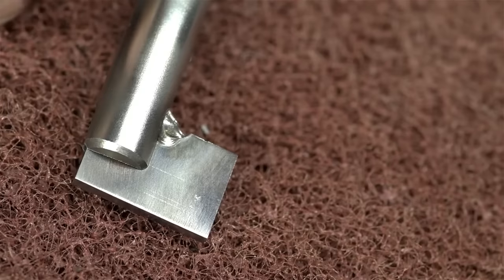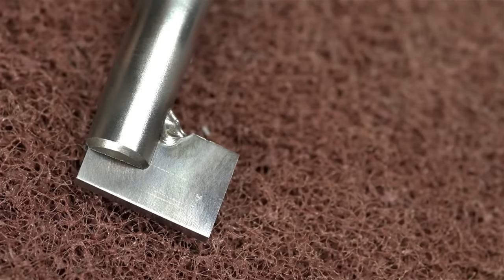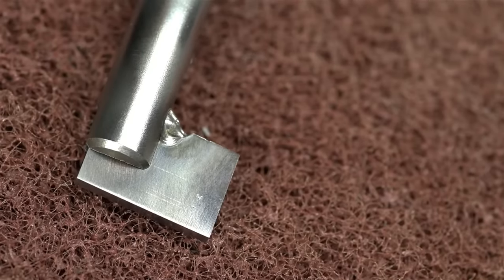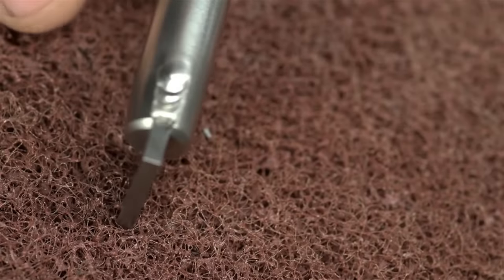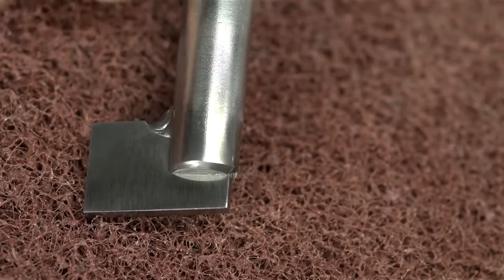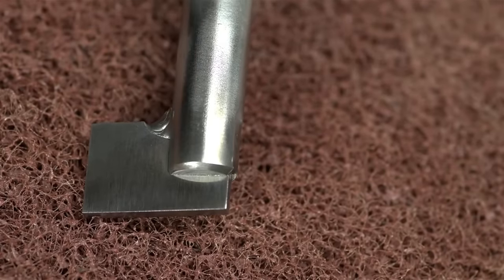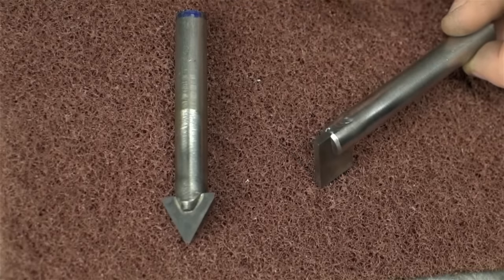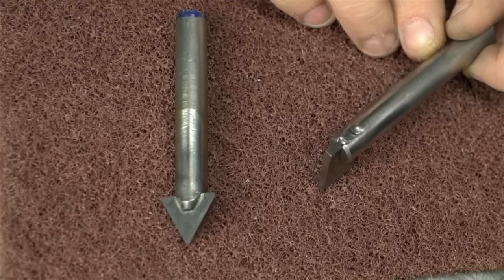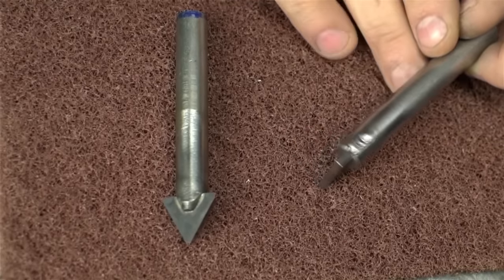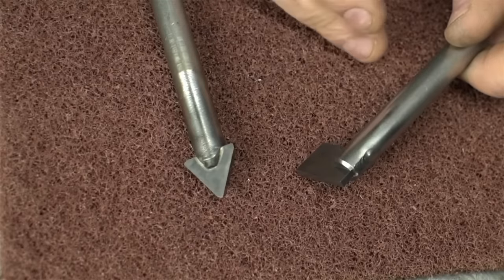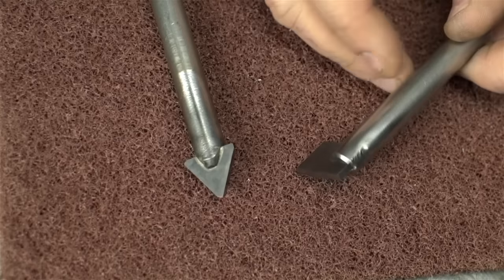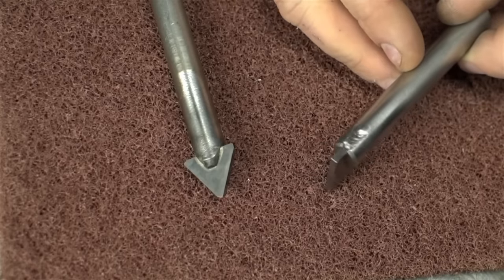And there you have it. Now, of course, with TIG welding, where it's welded, the high-speed steel is absolutely obliterated. But if you get in there quick, weld and get out without having to soak the whole piece, the high-speed steel up at the cutting edges is perfectly fine. Now, I made this to look like the shaper tool. I mean, this is how I made the shaper tool, just for continuity's sake. But in both these cases, you certainly could put on whatever shape, high-speed steel or carbide you need for the work you need to do.